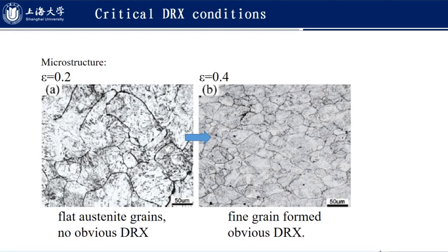This figure shows the critical dynamic recrystallization conditions for the steel. We can see from strain of 0.2 to strain of 0.4, the austenite grains show a totally different appearance. And this figure shows fine grains formed, which indicates obvious dynamic recrystallization of the steel.